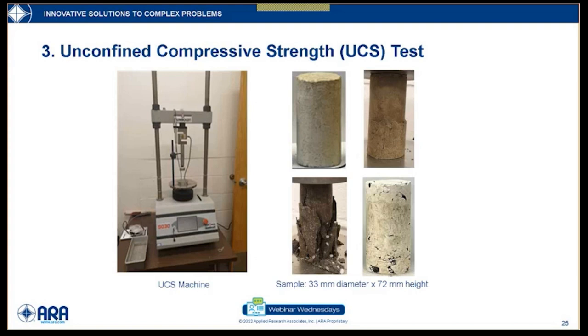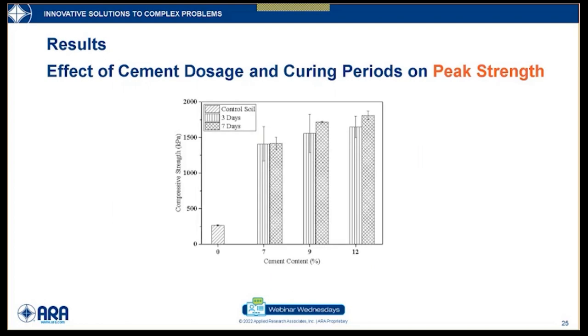The UCS test is important to understand how much load the soil sample can take before failing. It's also important to understand whether the soil is going to satisfy the strength criteria for any pavement application, like the soil subgrade strength criteria. And the results of the UCS test show that by increasing the cement content, the compressive strength also increases, and the strength also increases from 3 days to 7 days, like the more the curing days, the more the strength observed.